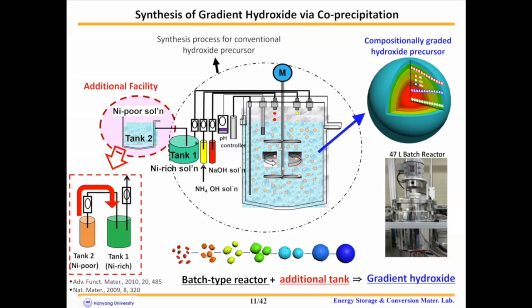This is the schematic diagram of the synthesis of the concentration gradient hydroxide precursors by co-precipitation. We can use the same facility used in synthesizing conventional hydroxide precursors. The additional facility is one solution reservoir tank. As you can see in this figure, nickel-poor solution in tank two is slowly pumped into nickel-rich solution in tank one, where the mixed solution is fed into batch-type reactors, leading to a smooth concentration gradient of transition metals within the particles during the co-precipitation process.